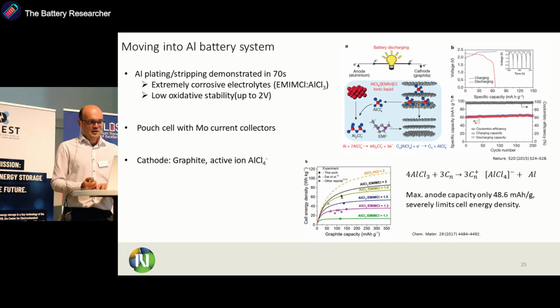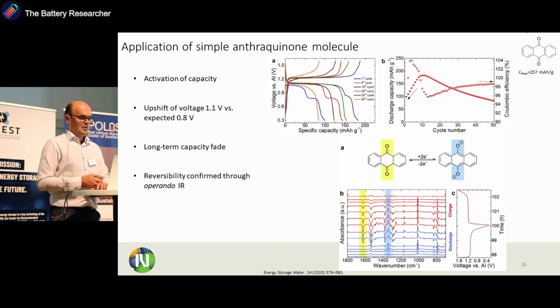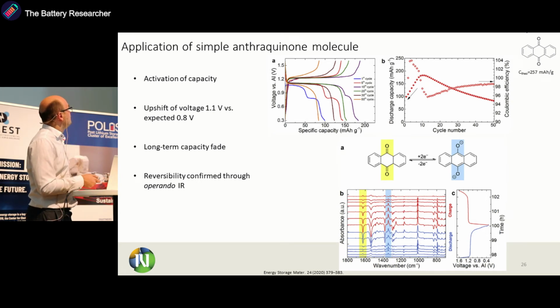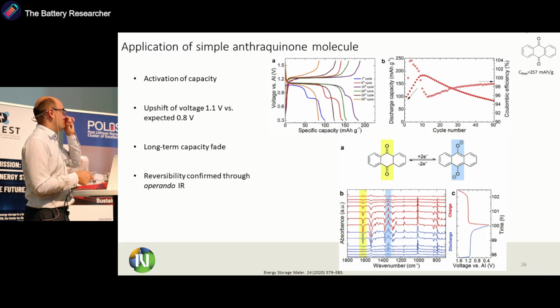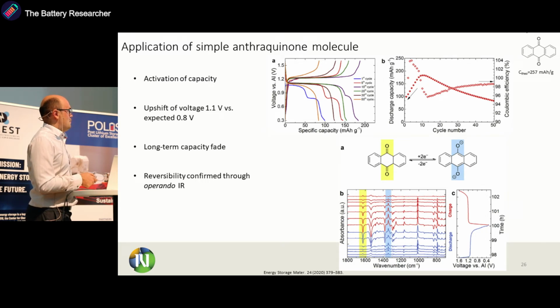per gram. So now we wanted to see what does happen when we put organic cathodes, and again we start with this anthraquinone, and we saw that basically it performs quite well. We have good reversibility, a bit interesting behavior because we have some activation of capacity, and also at start we have two plateaus, so one at 0.8 volt and one at 1.1 volt. But then the capacity slowly fades.